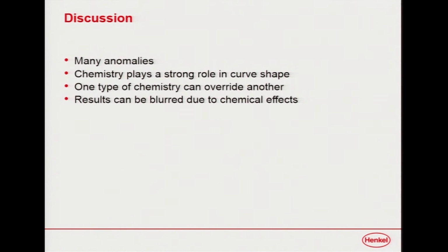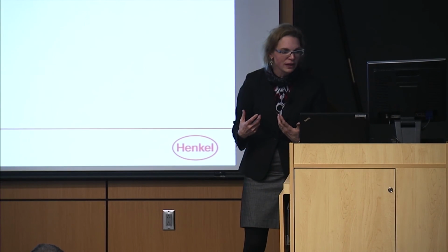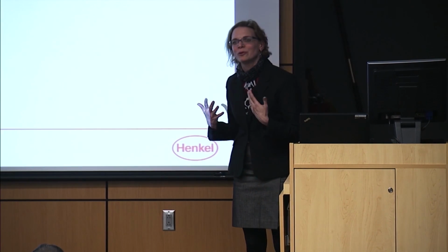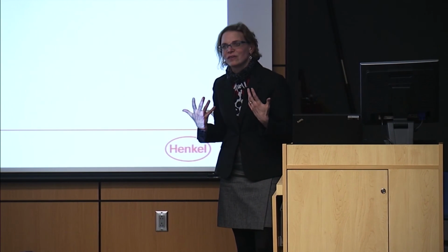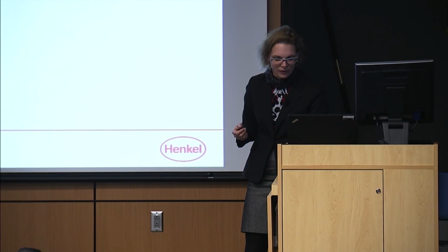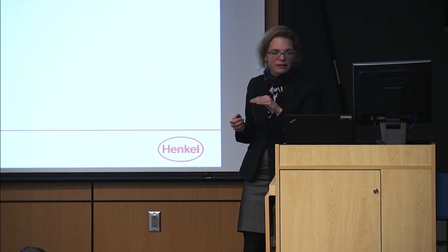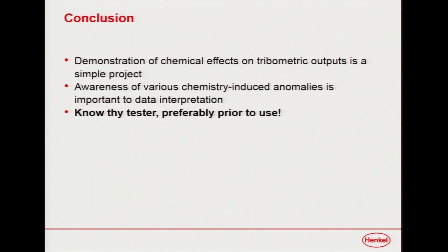And we found that not only does certain types of chemistry have these predictive curves, but they can override other types of chemistry. So we can get very specific about which regime we're active in. And sometimes you can get a little bit of blurring. So when we looked at those correlations, we could see that sometimes things didn't line up that well. But the chemical effects in tribometric outputs turned out to be a relatively simple project, but it was very, very dependent on having the right equipment.